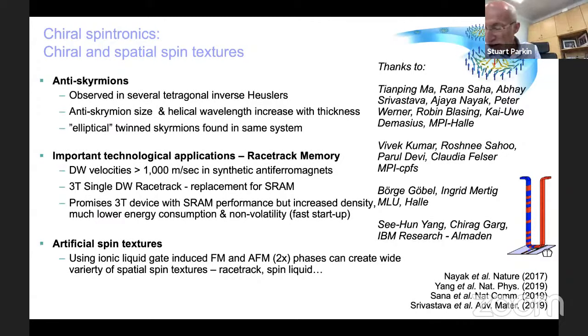So, you know, it's like growing all these thin films. It turns out, depending upon the complexity of the material, like the Heusler compounds are super difficult to grow in thin film form. But we did achieve that. In my former group at IBM, we used something we called chemical templating layers, L10 materials, in which we were able to stabilize for the first time a single unit cell thick Heusler layer. It was a binary Heusler, but we can use the same technique for ternary Heuslers.